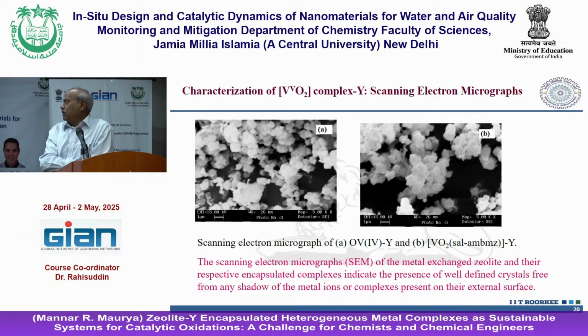But once the metal complex has formed and is washed thoroughly to remove any metal or metal complex from the surface, you will see sharpness in the crystalline nature of the zeolite. That gives the feeling that the crystallinity of the zeolite is still maintained after encapsulation of the metal complex. Only that much information the morphology can give.